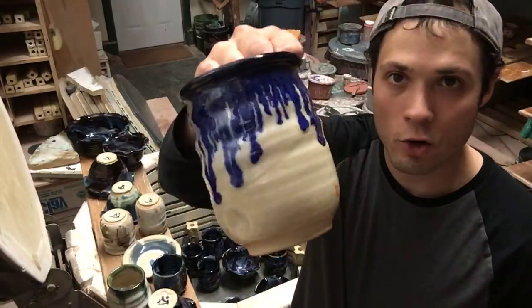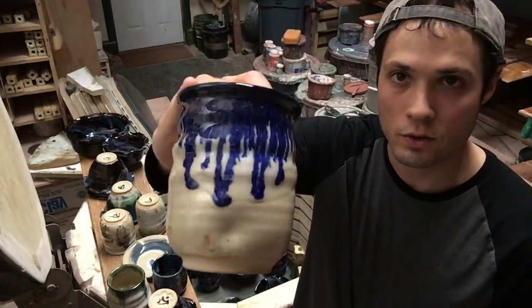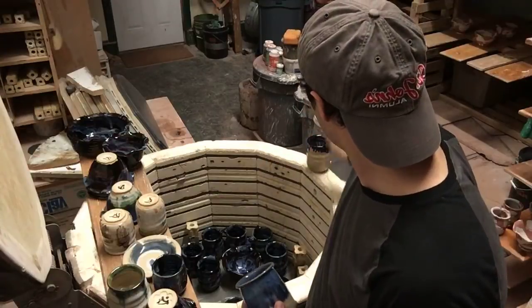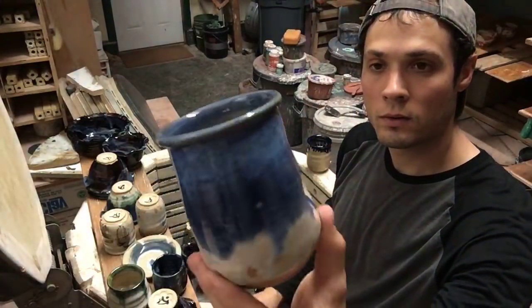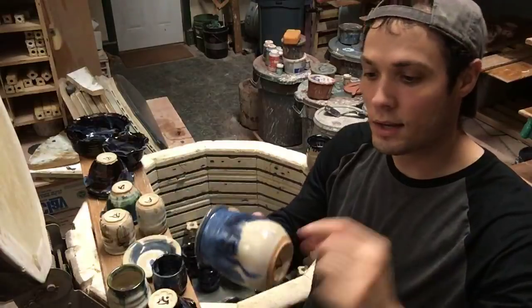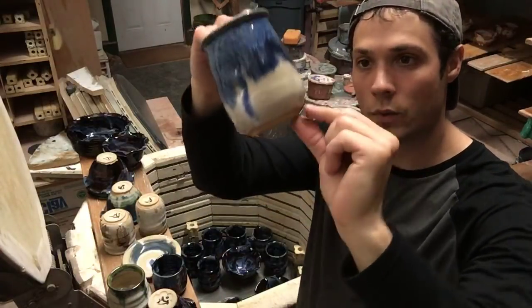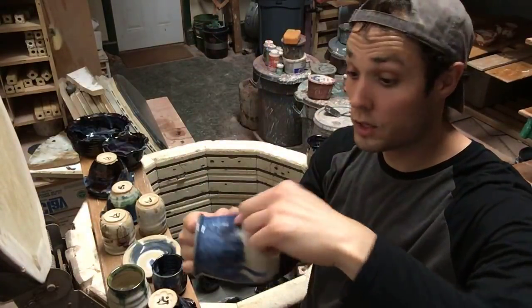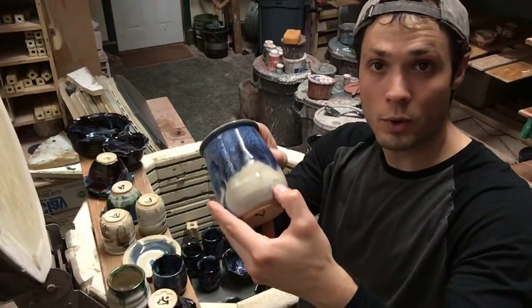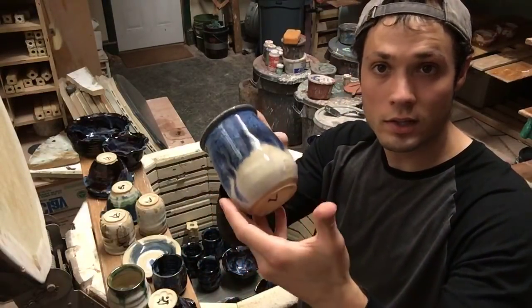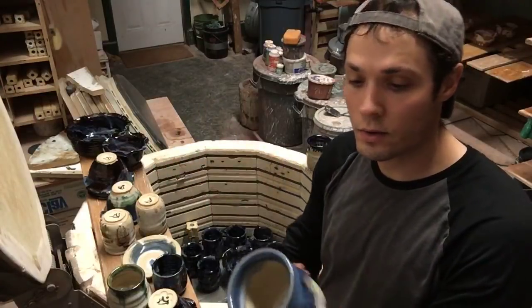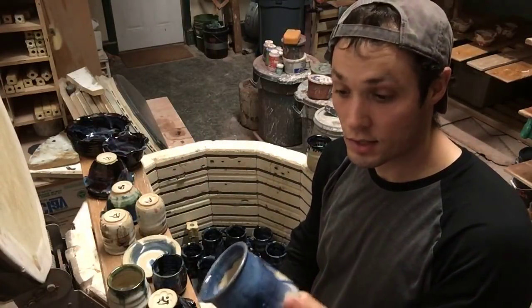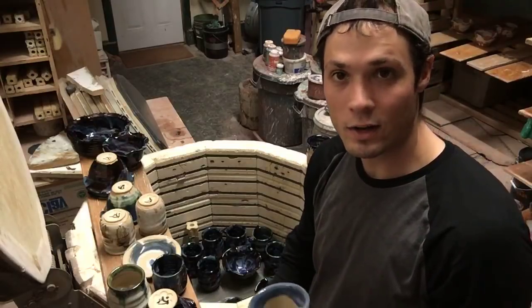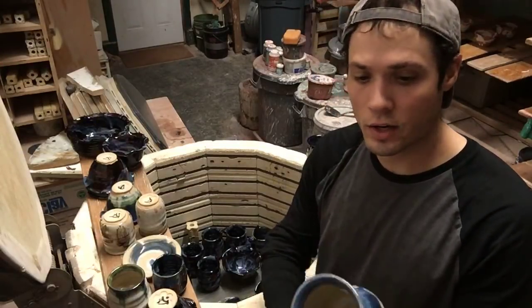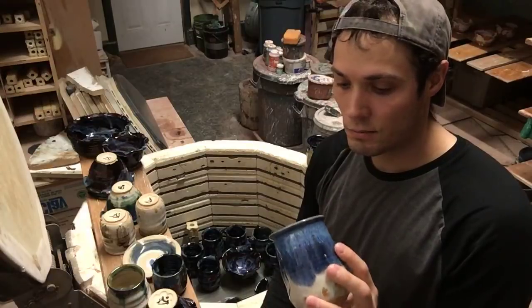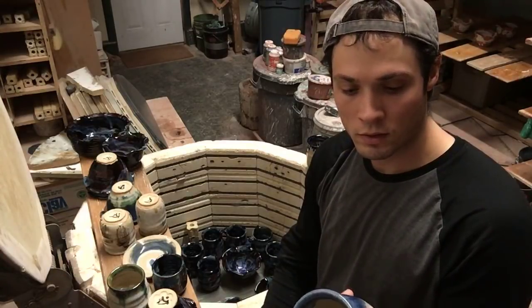Like cobalt. That has cobalt on the rim. It's just obvious that that's cobalt. It's so crazy intense. So this, I mean, I can see that I dipped it down into the Nuka glaze all the way down here, and I can see that I dipped a clear glaze all the way over the Nuka because my thumbprint from where I was holding it, that's glossy. And I know the thickness of the oil spot glaze, and it's thin. So by thinning the glazes out, I used to use really thick glazes to try to get intricate colors. And by going thin, man, they're really starting to do a lot.